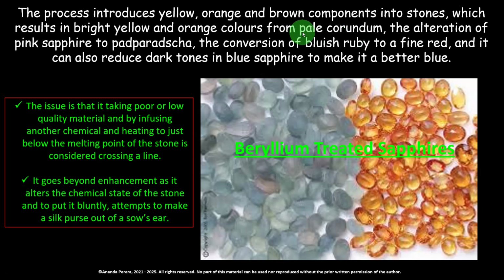With this treatment, beryllium treatment, pale corundum colors can exhibit vivid colors. The alteration of pink sapphire to padparadscha, the conversion of bluish ruby to a fine red, and it can also reduce dark tones in blue sapphires to make it a better blue. Very dark stones can become a better blue with the beryllium treating. The very, very dark blackish blues can't sell, so we can't get the color from those stones, but it is not a good thing. These are the beryllium treated sapphires.